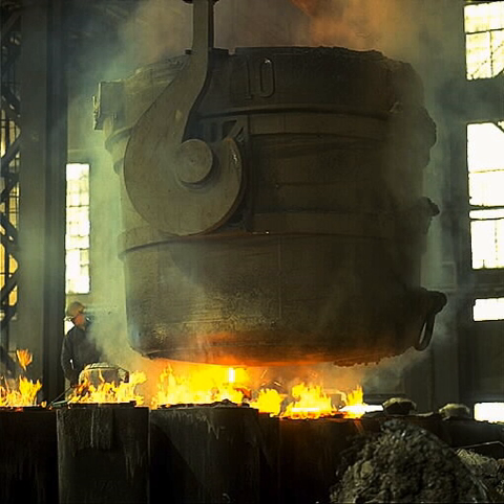Phosphorus and sulfur may be burnt out of the molten iron, but this also burns out the carbon, which must be replaced. Depending on the application, carbon and silicon content are adjusted to the desired levels, which may be anywhere from 2 to 3.5% and 1 to 3%, respectively. If desired, other elements are then added to the melt before the final form is produced by casting.